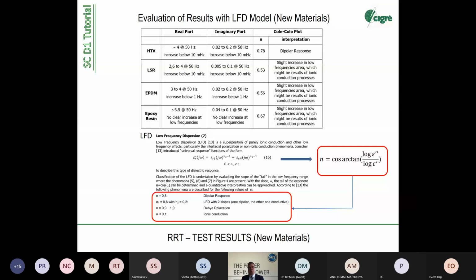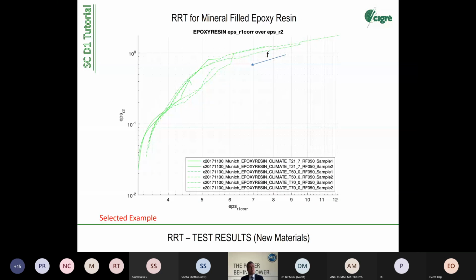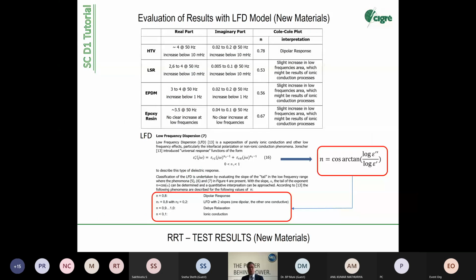But with all the data, what do you do at the end? We cannot, for example, need an expert to look into such diagrams and to decide whether it's good or bad or what you see from it. In the theory for later applications, we have to bring this to a quantitative figure that we can say, okay, here we see this kind of effect, or we see no effect. And for this reason, we applied the theory of low frequency dispersion. Why again low frequency? Low frequency because we see in the low frequency range the Maxwell-Wagner effect. We see all effects that are interesting and important for composite insulating materials.